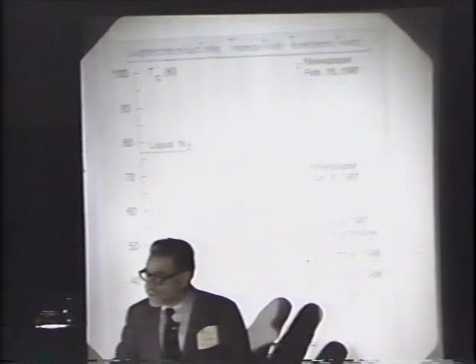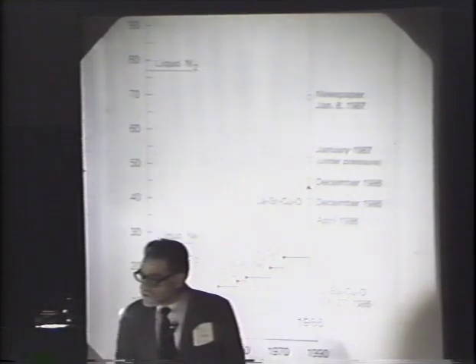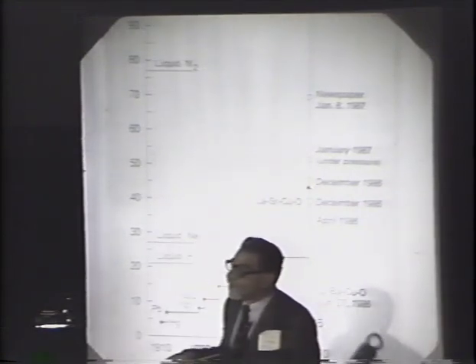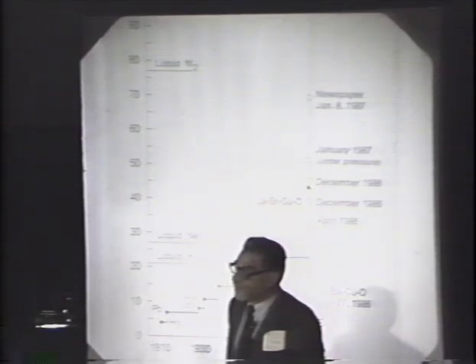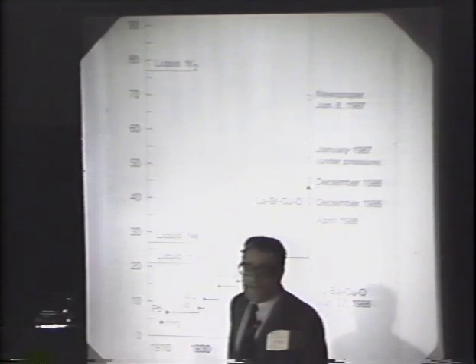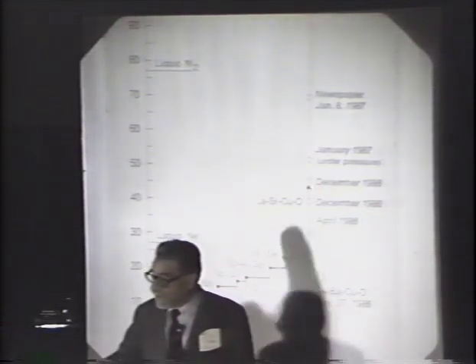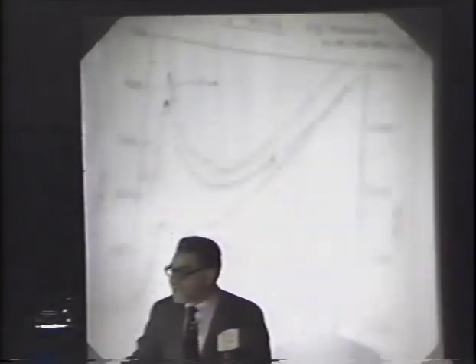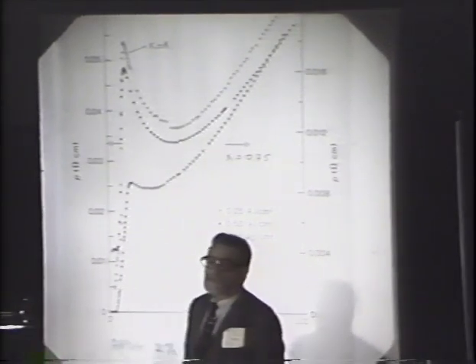here I have plotted the confirmed results by the group of Professor Chu, is well toward the 100 degrees Kelvin. Now, the first observation in the new system dates back to January 27, when we saw the onset in the lanthanum barium copper oxide mixture, and by optimizing the substitution of the lanthanum by the barium, we were in April up in the 35 degrees Kelvin range, and I show you the data which we submitted at that time. So essentially the whole search extended over about 2.5 years.